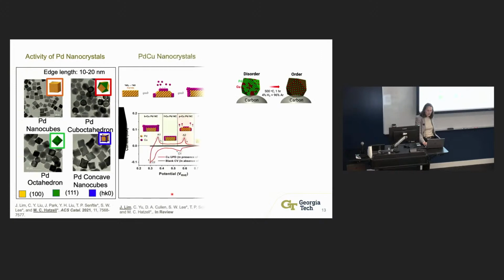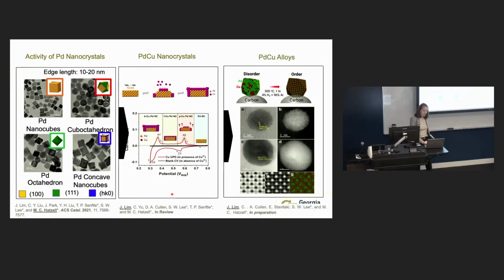And so this is, again, work that was completed by Junghoon. What he first did was look at how you create these nanocrystals through controlled growth. It's really easy to, well, it's not easy, but a lot of times when looking at facets and looking at fundamentally what's happening at a surface, people like to create films with certain exposed facets. So we can look at what's the effect of a 100 facet or a 111 facet.